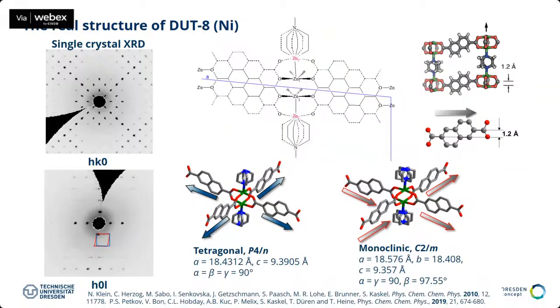Now, for a long time, we were very much struggling with the real and detailed structure of this kind of material. When Michael Sabo came for the first time to my laboratory with the single crystal structure, he said, this looks really ugly. He came up with pictures which looked like this. So it seems that the naphthalene ring looks totally disordered. And you can see this also in the single crystal X-ray data. There are lots of streaks here, multiple peaks basically. This doesn't look like a good single crystal structure. And many people then say, this is also typical for science, then it's not a good structure, let's not look at it more in detail, or let's ignore it basically.